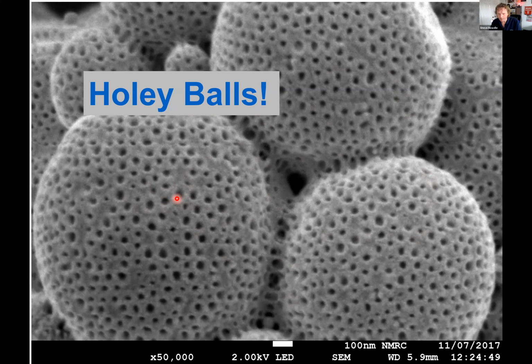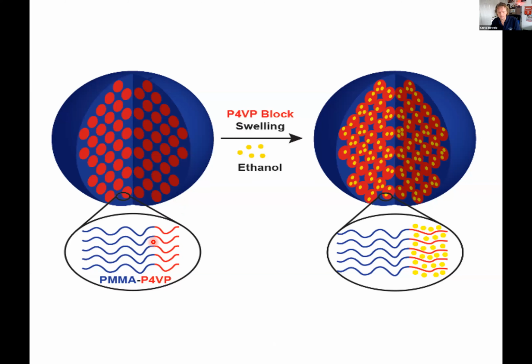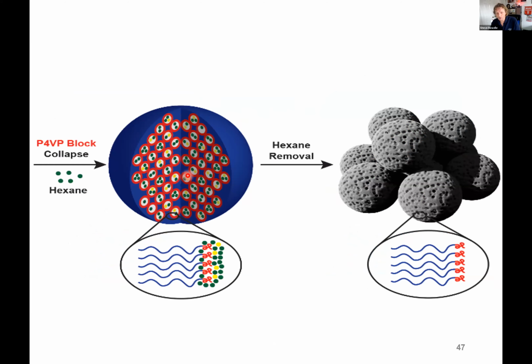Now, how has this happened? We had to look at it very carefully. What we understood was that if we added ethanol, it would preferentially go into the vinyl pyridine zone and swell it. Then if we added a little bit of hexane, it would cause this to collapse, forcing out the ethanol because they don't like each other. This hexane removal and forcing out of the ethanol caused the porosity to appear.